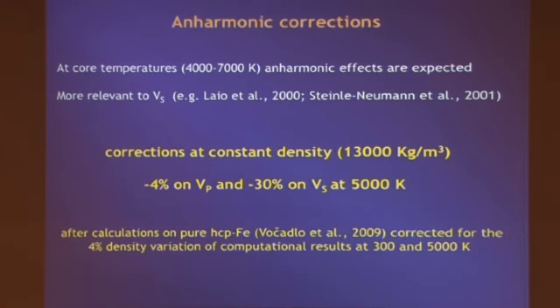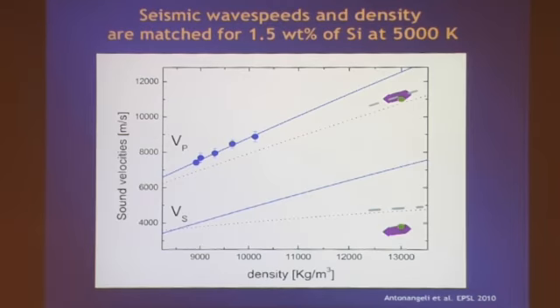And if we add this other ingredient in our minimization, we end up with these two green dots. So we have a solution to the main seismic observables, the seismic wave speed, both VP and VS, and density, for a model composition of 1.5 weight% of silicon at 5,000 Kelvin.